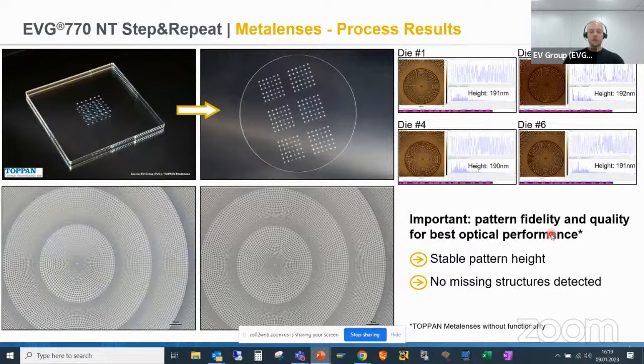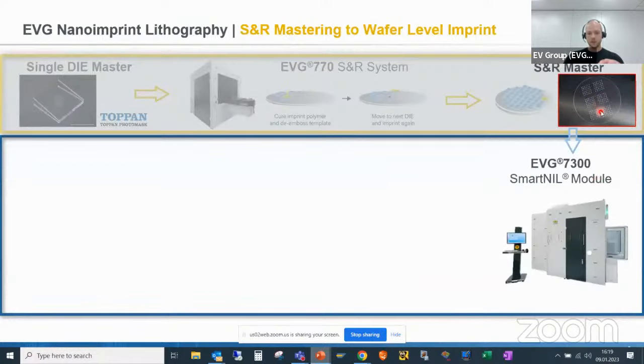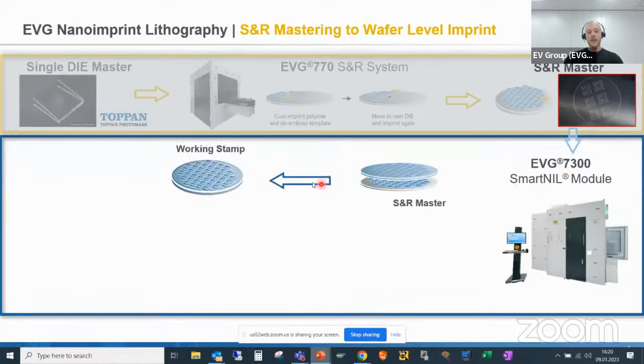After the step and repeat master is created, we take this master and coat a working stamp polymer on top. With this coated master, it will be loaded into an EVG SmartNIL module. This can be a standalone tool for R&D purposes, for example, or even high volume manufacturing. We create a negative polarity working stamp from this fabricated step and repeat master, which we have created in previous steps. This working stamp will then be attached to an imprint substrate where we have coated a NIL resin. This can be a standard refractive index, high refractive index, or low refractive index according to the customer's needs.